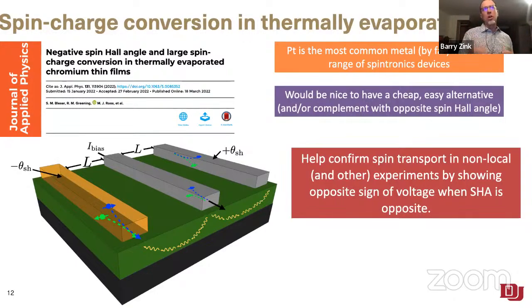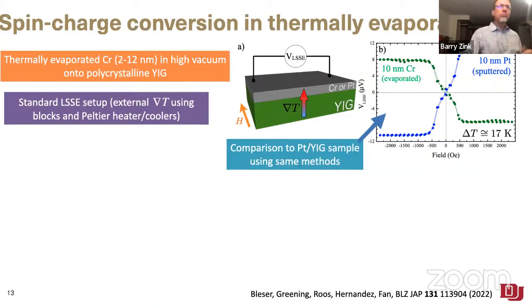And so we started working on thermally evaporated chromium for this reason, because it's cheap, it's very easy to produce in e-beam lithography via liftoff. You get nice sharp features and all that kind of thing. And so it seemed like an easy thing to try just to see if it worked. Sort of expected that it would at least give a signal because of the work that had already been done on sputtered chromium. And so we went off down this road to try to figure out whether thermally evaporated chromium thin films displayed spin charge conversion.